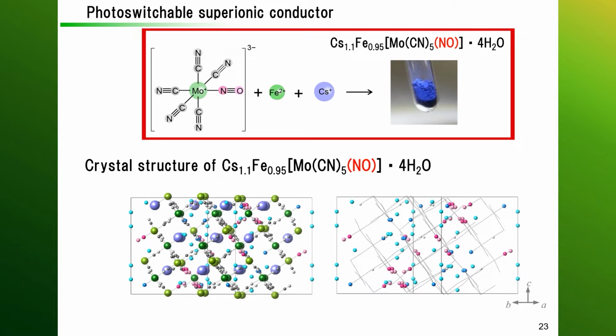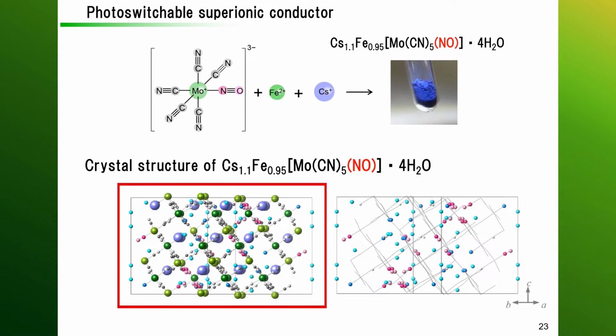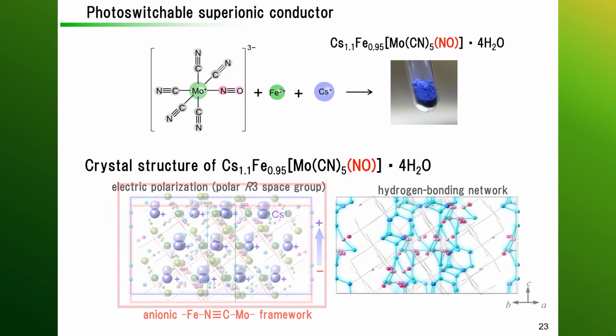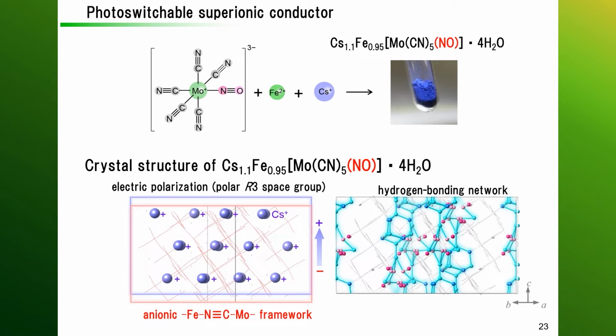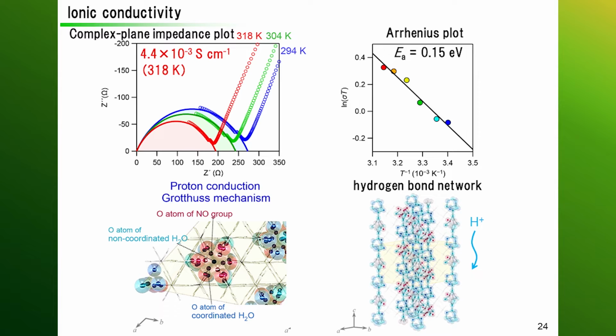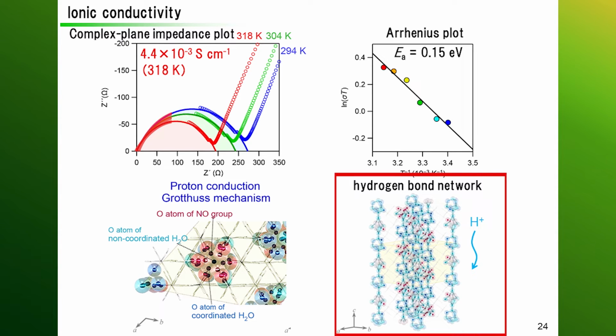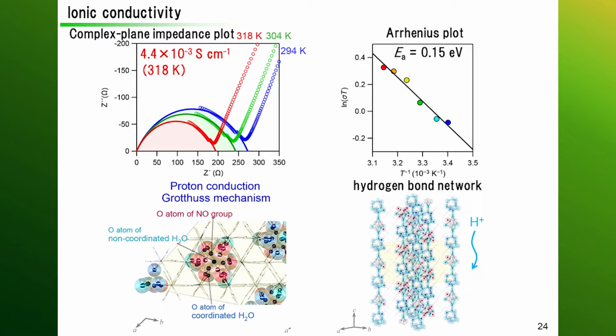Here's another similar material synthesized by mixing molybdenum ions, iron ions, and cesium, and the color is bright blue. The bottom of the slide shows its three-dimensional network of the crystal structure, rather a unit grid of a much broader network. The complex plane impedance plot of this material shows that proton conduction is induced with a trigger. The structure has hydrogen bond network internally in which protons can transit. The result shows that this is an ion conductor or a proton conductor.